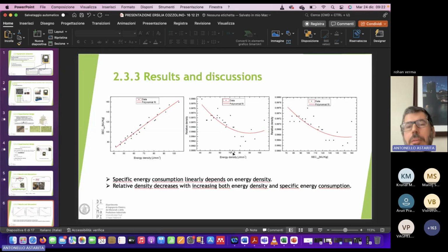because in additive manufacturing, to achieve the maximum density of the parts, your main aim will be, of course, to achieve a relative density of 1, but it's very difficult. Here we have, as you can see, 0.99, so we achieved extremely high density of the final parts, but you can see also that there is a correlation between the density of the part and the specific energy consumption. Okay. So again, another point in sustainable advanced manufacturing is to link the performance that you are seeking, in this case, the density of the printed parts, with the amount of energy and the impact that you are generating to produce those parts. So again, something that you have to consider.